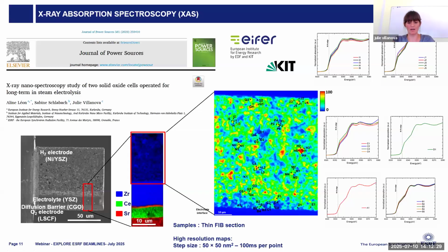electrolyte. And what can happen is that working under a current and at high temperature, you can have diffusion from one chemical element to another that will also create some detrimental layers at the interface between the electrodes and the electrolyte, where you have the electrochemical reaction happening. What we can do at the beamline is first, using the XRF, map the different chemical elements. Here you have the electrolyte and the hydrogen electrode represented by the zirconium, the diffusion barrier represented by the cerium, and we find the strontium in the oxygen electrode.